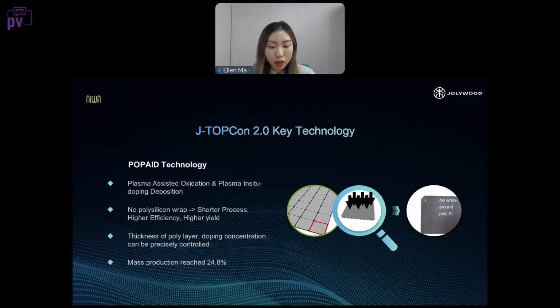Under this technology, the tunnel oxide will be more uniform compared with the standard process, which means we can ensure that there is no poly wrap-around, so we don't need an additional cleaning process. Moreover, under this process, the thickness of the poly layer and the doping concentration can be easily controlled, which means we can successfully increase the efficiency and also the yield. According to the data from our factory, modules applying TOPCon 2.0 technology can have a maximum production efficiency of more than 24.8%.